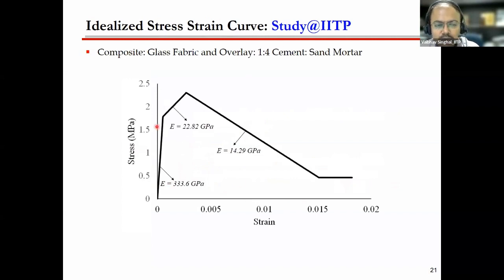Now this is how a typical stress strain curve you may obtain. This is one idealized curve which we have obtained when we tested the reinforced cementitious matrix, where the reinforcement is provided by using the glass fabric, and the cementitious matrix was simply a cement sand mortar of 1:4. So this is one test which can be used to find out the tensile properties of this reinforced cementitious matrix.